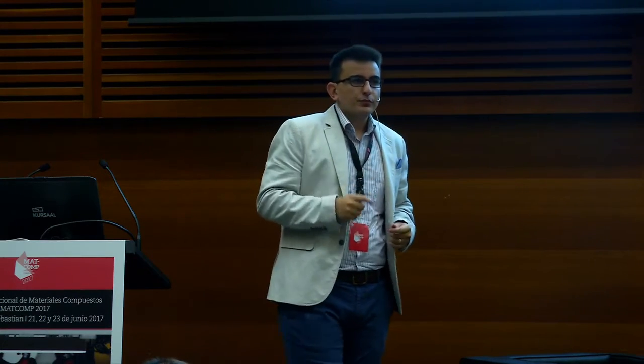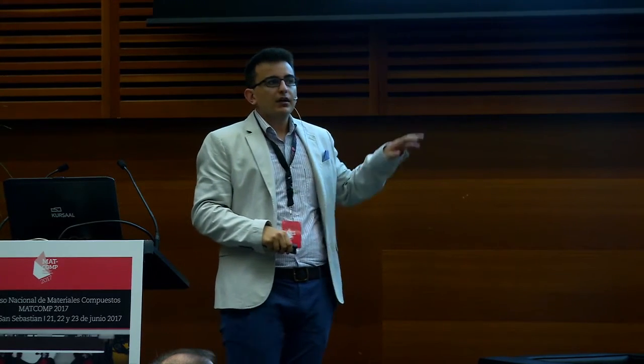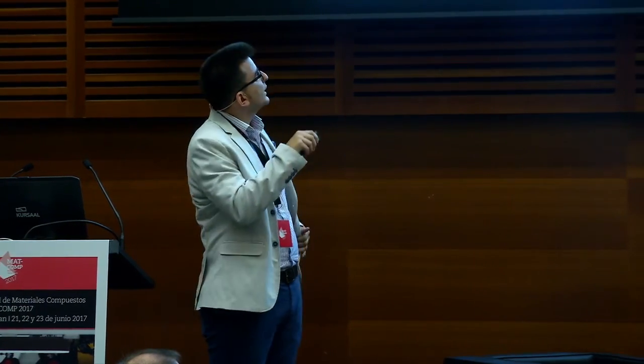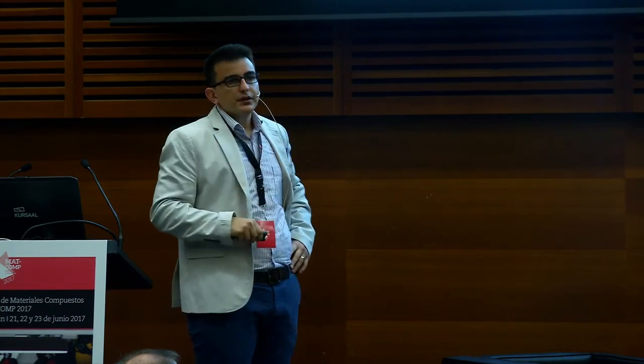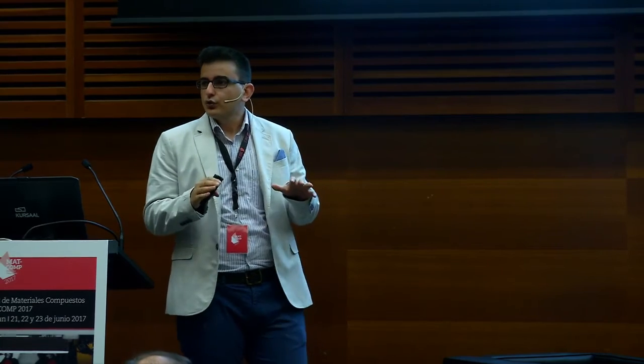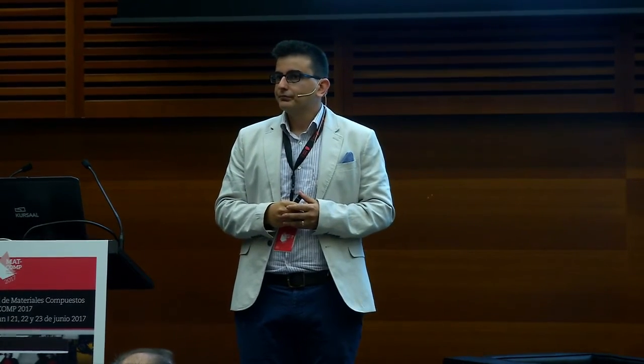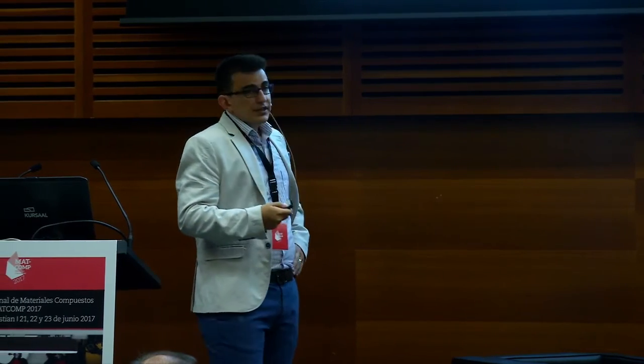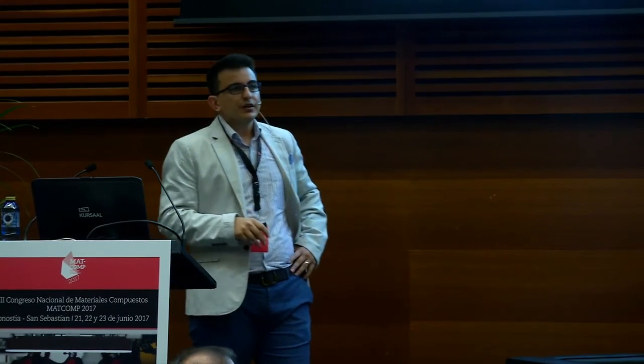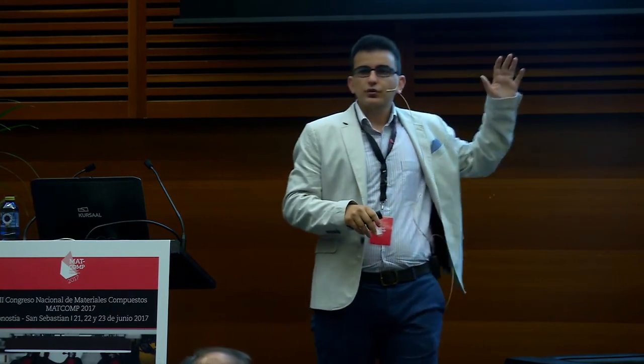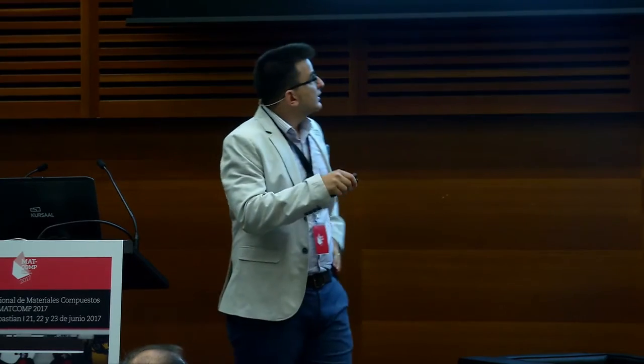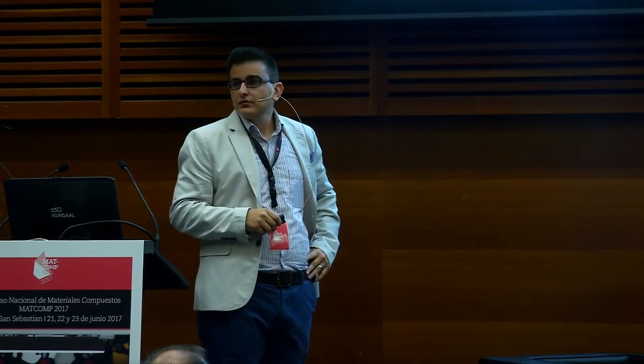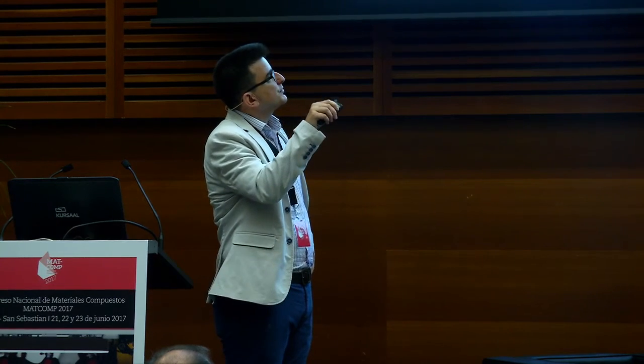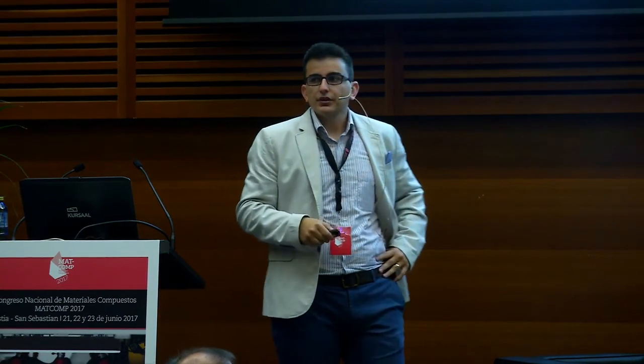If we apply a deterministic process optimization, obviously we improve the pulling speed, but now with the statistics, we have a worse probability. Now we have 50% chance that the degree of cure can be smaller than 0.9. So let's compare the results of reliability-based optimization. Now we are able to shift these two curves to the right-hand side, such that now we have 1% chance, and still we improve the pulling speed substantially.